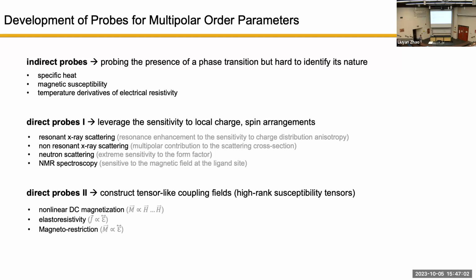Okay, but more recently, there is another direct technique. That is to say, I'm not having the sensitivity to the locality, but I'm still sensitive to this kind of phase by the fact that now I can couple into the so-called tensor order parameter. I create a so-called tensor field, then use the tensor field to couple into the tensor order parameter. To induce the tensor field, typically you have to go to higher order processes because our typical fields are vector fields. Okay, so it is this newer technique that inspired our work of trying to use nonlinear optics to study multipolar order, because naturally for us, optics has developed in a way that driving nonlinear response is no longer challenging anymore because we have very short pulses now.